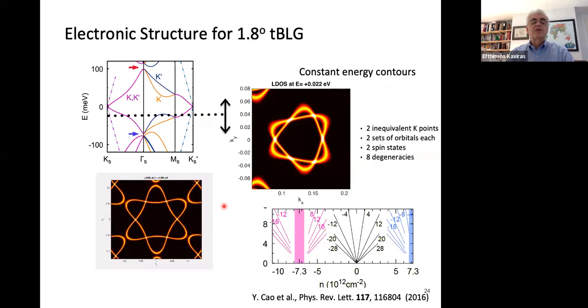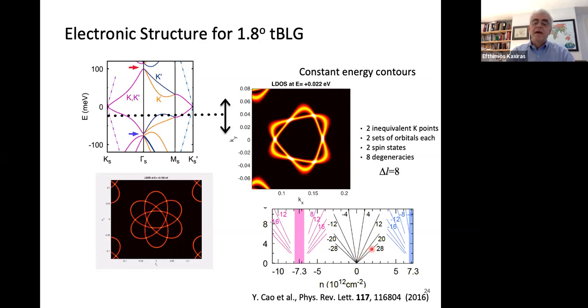So using this formulation, Xiang was able to model what happens when you dope this bilayer system, and this is basically moving the Fermi level up and down and produces these constant energy contours. One example is shown here. And by simply counting now the degeneracies of these constant energy contours, you can easily account for the total degeneracy, which gives you a handle of the jumps in the Landau level index and very nicely explains what is seen here in experiment, as I mentioned earlier.